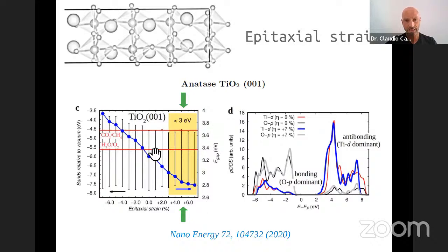At some point, it's reduced to below 3 electron volts, which means you have changed the light absorption properties in a way that this material can be more efficient. On the other hand, the band alignments here, at 0 strain, were not optimal because basically they were not straddling the energy levels of interest. Here I just changed, so this is very close to the HER level, but okay, we just put in another reaction, but just imagine it's very close to the OER, right?